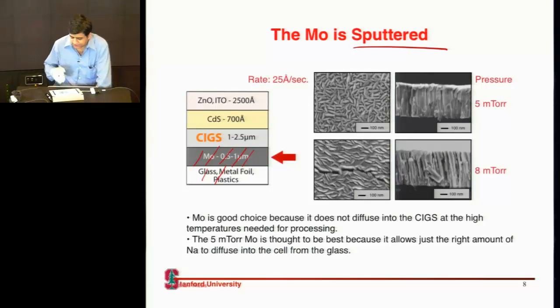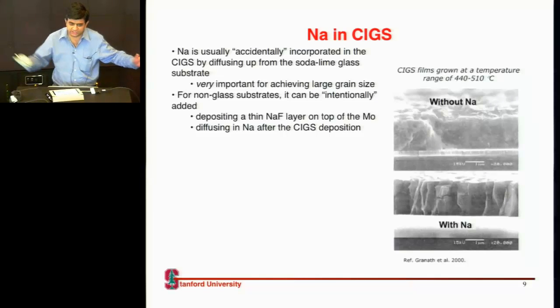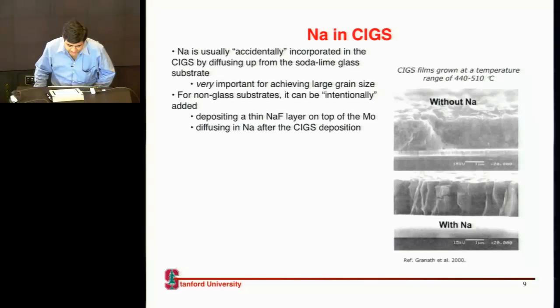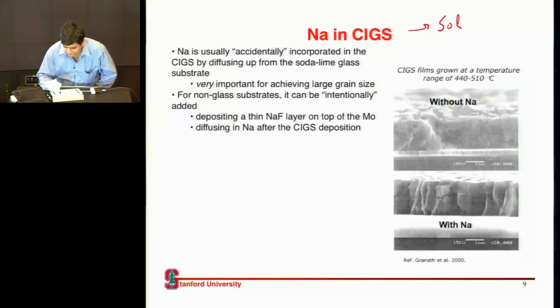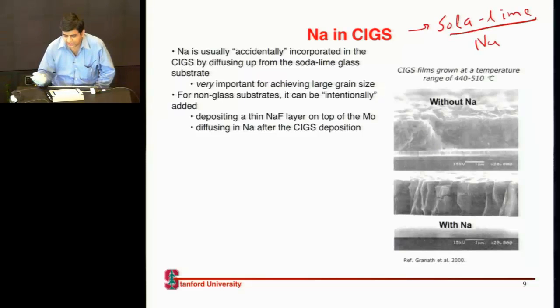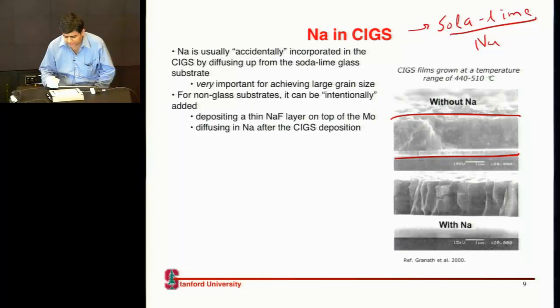People try to grow these layers on either glass or aluminum. The reason why glass is preferred in some cases is that these glasses are essentially what is called soda-lime glass. It's so-called because it has some amount of sodium in it, which is really helpful while you grow these materials — it helps in increasing the crystallinity. This is a cross-section SEM picture of your CIGS layer without sodium, and this is with sodium.